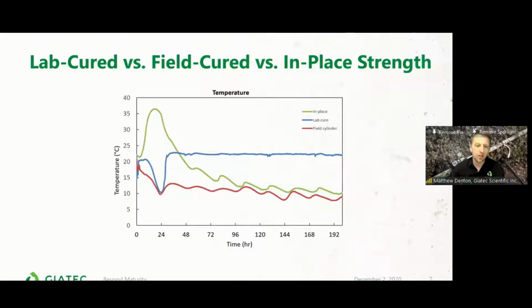Here you can see our green line is that spike if we're monitoring the temperature of our poured concrete. Whether this is a slab or a column, a 100 millimeter slab or a 200, 300 millimeter slab, we're certainly going to see a difference between the temperature of our on-site concrete versus the temperature of our concrete in the sample. So in the smaller element, in the smaller sample, there's a big difference there.